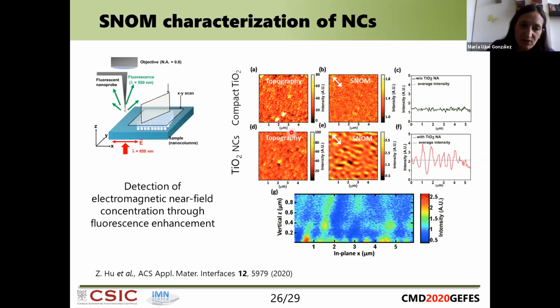And in the case of the nanocolumns, what you see is a much more modulated distribution of the intensity of the electric field. We have points where we have a high enhancement of the field, and if you compare the profiles, you see points where the intensity is much higher than the average, but even the average is higher than in the other case. So the presence of the nanostructure is already generating points of enhancement that could help increase the absorption of the perovskite. And this could also be an explanation of the higher absorbance that we got before.